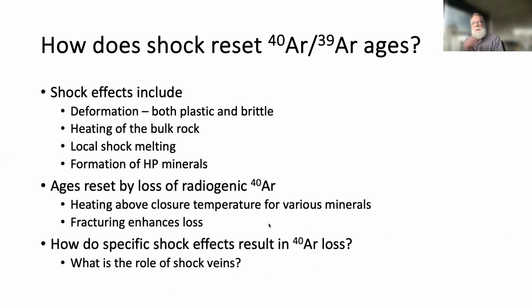All right, so we were interested in how shock resets the argon ages. We know the shock effects include deformation, both plastic and brittle, heating of the bulk rock, local shock melting, and formation of high pressure minerals. Clearly, the ages are reset by loss of radiogenic argon, and it's mostly from heating above a closure temperature for these various minerals. Fracturing also enhances the loss. And the main potassium-bearing mineral in these rocks is the plagioclase. So it's really the shock effects of plagioclase that determines the resetting. But we wanted to know how specific shock effects result in argon loss, and what is the role of shock veins.